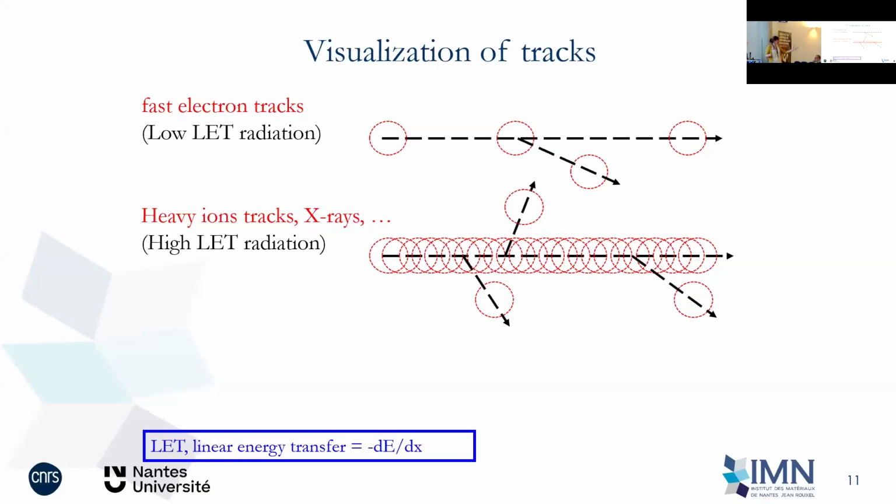So in case you don't know, this is a parenthesis here: X-rays are much more damaging than electrons. It's just that the doses that we use in the synchrotron are lower. And the reason for that is this. This is why they are more damaging. You're transferring much more energy to your material than an electron does. Okay, so these are usually the two different things that we have. And I'm going to be focusing on electrons.